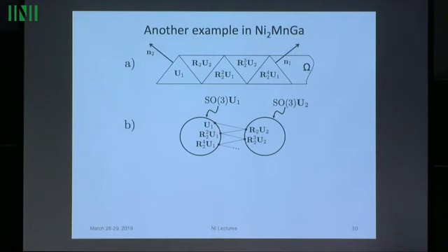So you start with U1 here, and suppose these are compatible wells. Then from what we said this morning, U1 is rank 1 connected to precisely two matrices over here. Take one of them. It is rank 1 connected to precisely two matrices over there. So of course U1 is one of them, but the other one turns out to be R2 squared U1. And this one is rank 1 connected to 2 over here, so it must be another one. So you can zigzag across these wells.